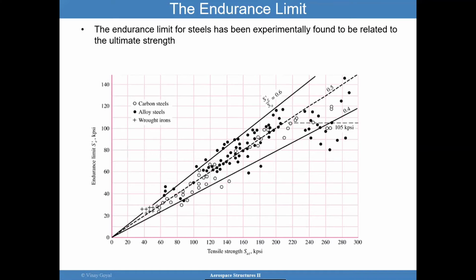The endurance limit for steels has been experimentally found and is related to the ultimate strength for most situations. You will see here some data. On the y-axis, you see the endurance limit. On the x-axis, you see the tensile strength. So there is a relationship where you can see here that the endurance limit is correlated with the tensile strength for carbon steels, wrought irons, and alloy steels. In general, you could use this data to guide you. Not having the data, you could try to make some assumptions that could be of help. That is what I want to point out here.